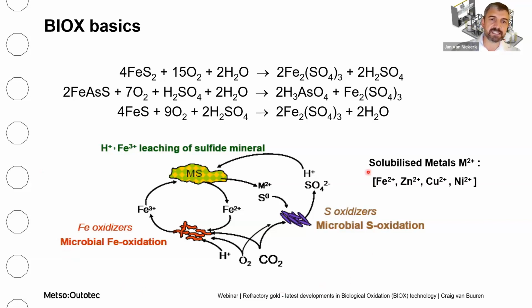This picture at the bottom shows the typical leaching mechanism during bioxidation. The bacteria do not actually oxidize the metal sulfide directly, but the bacteria will just regenerate the ferric that is the oxidant for the leaching of the metal sulfide. You'll typically have two types of bacteria in your tank, your iron oxidizers and your sulfur oxidizers. Elemental sulfur is oxidized all the way to sulfate. It is important to note that you will always also need a small amount of carbon in the form of CO2 for biomass production during bioxidation. This is normally supplied through the solution of carbonate minerals in the concentrate.